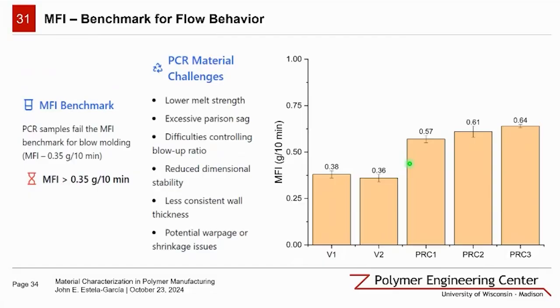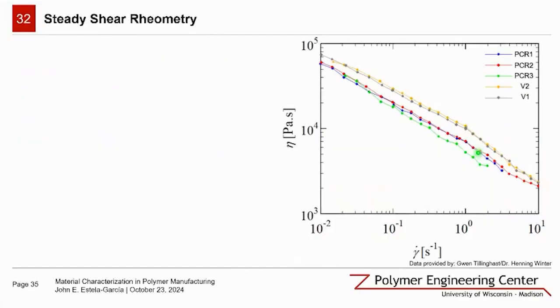The PCR material fails to meet these benchmarks, so their lower melt strength may lead to parison sag or difficulties controlling the blow-up ratio during the formation of the bottle. And this can result in reduced dimensional stability and less consistent final properties. Additionally, we can also see warpage in our system. So utilizing these PCR materials may necessitate adjustment of processing temperatures. These findings underscore the complexities of incorporating PCR materials into blow molding processes.